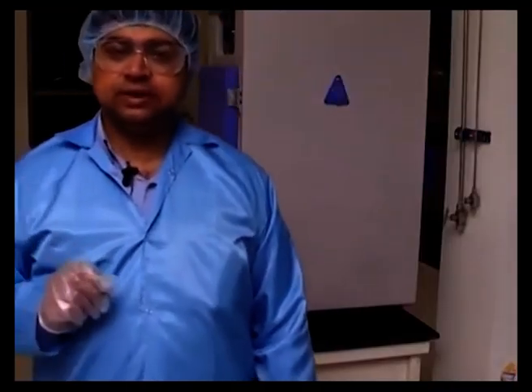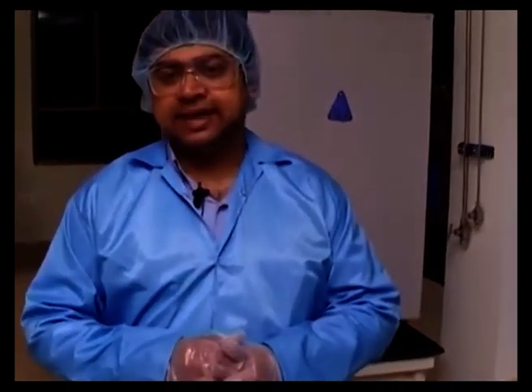So the next stage is spin coating the photoresist, and for spin coating the first thing that one needs to take care about is the grade of resist that one is using. There are many manufacturers of resists in the world. We will be doing negative tone photoresist here, which means that wherever light or UV light is used for exposure of the photoresist film, there would be a general cross bonding among the molecules, and the resist stays back, and the portions which are unexposed can be developed off. So what you have is small features translated from the mask design onto the resist surface. Wherever light has fallen through the mask window onto the resist, the features remain. The other portions go away after developing.